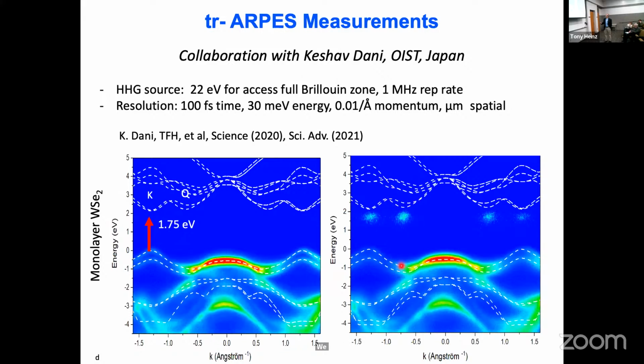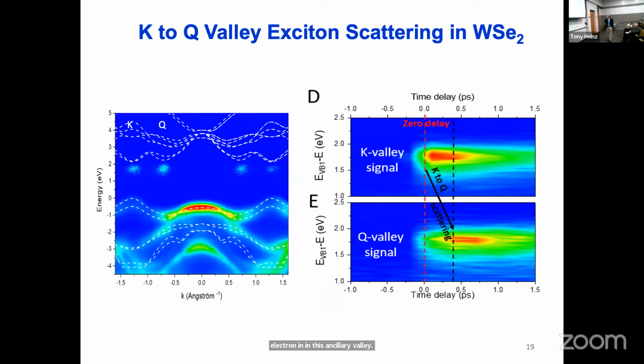Just to give you an example, this immediately told us there was another type of exciton here, which had an electron in this ancillary valley, called the Q valley. And we could immediately use that to study the dynamics. So when we looked at photoemission at an early time, we promptly saw the signal from the valley in momentum space where we excited the electrons, the K valley, but only after a delay time of a couple hundred femtoseconds did we see this new kind of exciton form. So that was an inter-valley scattering process. And in fact, we'd had various clues that it might exist, in terms of broadening of experimental lines and temperature dependence of broadening and things of that sort. But this gives you a very direct picture of the character of the excited states in the system.